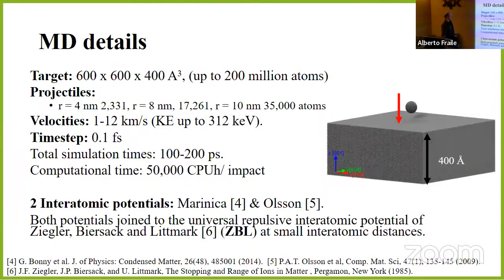In the simulations, we have a target that is just a box full of atoms, with a size of more or less 600 times 600 times 400 cubic angstroms, up to 200 million atoms in the largest simulations that we did. We changed the size according to the kinetic energy of the impactor. For very high velocity, we use very big targets. The projectiles were spheres of 4 nanometers, 8 and 10 nanometers, comprising 2,000, 17,000, and 35,000 atoms approximately. And the velocities were from 1 to 12 kilometers per second for the small impactors, reaching kinetic energies of 312 kiloelectron volts in the highest ones.